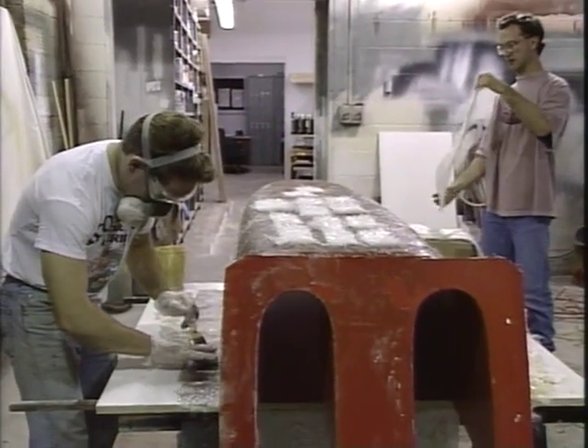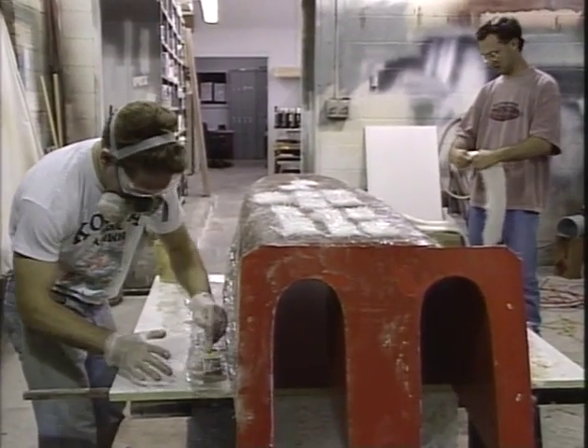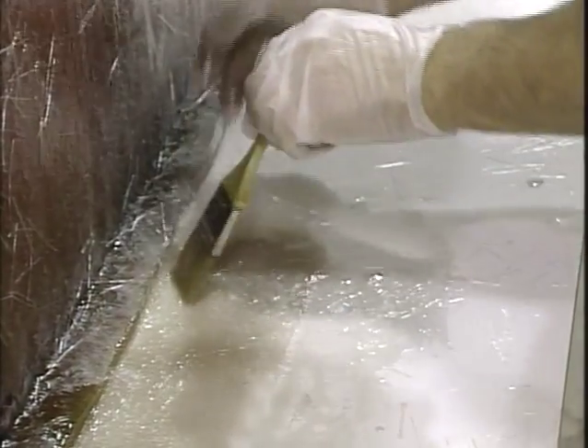Next, the mold was inverted on a waxed Formica board where 5-inch wide strips of chopped strand mat were butted against the existing flange. These were added until they matched the height of the original. Then, wider portions of mat were overlapped onto the mold and the flange. When the flange matched the thickness of the rest of the mold and was continuous around the full perimeter, it was allowed to cure, and then it was released from the Formica.